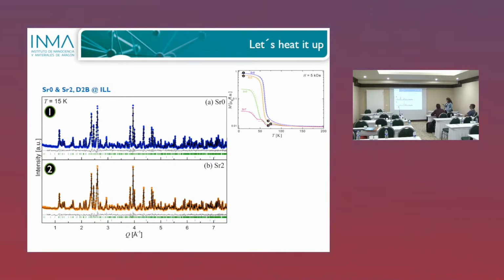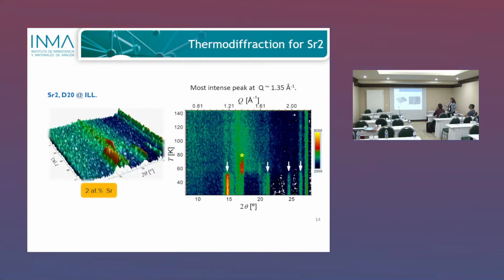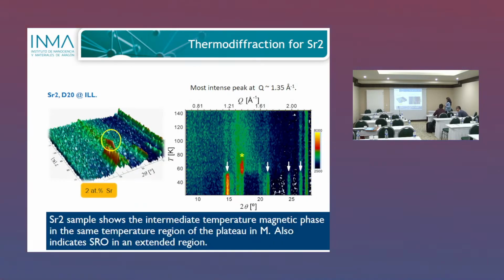So if you have a look at the sample with 2% strontium doping, the diffractogram looks quite the same. And so we focused on this region, because here is where the magnetic signal is higher, and you can see if there's something going on in the magnetic order. So for this, we did thermodiffractogram experiments, which means that you vary temperature as you collect the diffraction patterns. And indeed, even for only 2 atomic percent strontium, we did observe that there was something going on between 62 and 82 that manifests with this peak and this other peak here, and some other small features. But indeed, the white arrows indicate the ferrimagnetic phase, and this is another phase that is different. So what was this second phase appearing there?